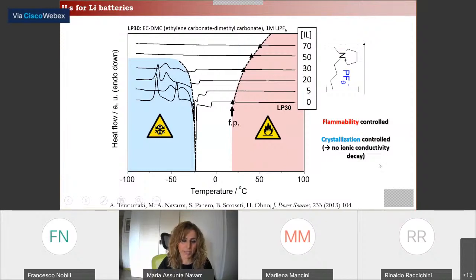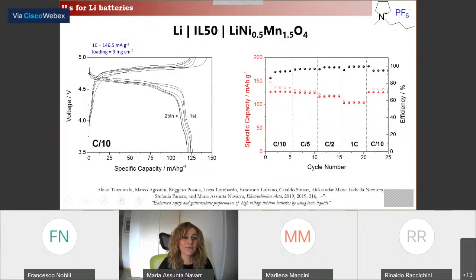The mixed electrolyte, composed of 50% of ionic liquid in LP30, was successfully used in a lithium metal cell, in a high voltage lithium metal cell with this lithium nickel manganese oxide spinel cathode. And here I'm showing the voltage profile in charge and discharge, and also let me stress that the Coulombic efficiency of this cell was improved when the current density rate was increased.